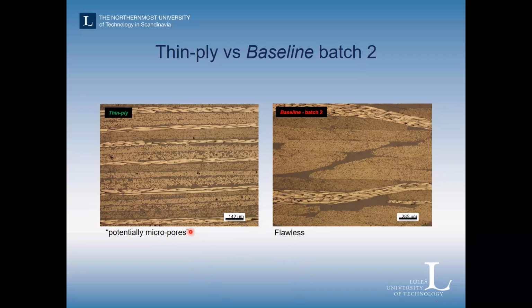The thin ply appeared to be better when we first looked at it, but after a bit closer scrutiny, we found that there are micropores also in this material that could create pathways for oxygen and accelerate the degradation of these materials. Despite the fact that we didn't see any transverse cracking in these materials, we didn't see any improvement from a degradation point of view.